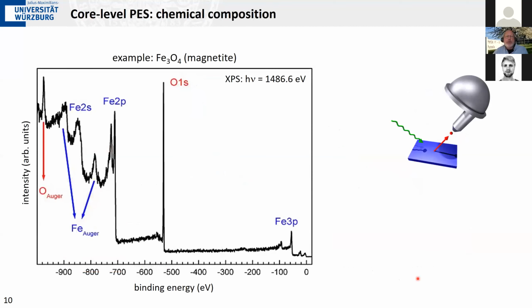Okay, this is what this looks like if you look on a large energy scale. This is an example: an XPS, X-ray excited photoelectron spectrum from magnetite, which is an iron oxide. In your spectrum, this is the current or the intensity of the photoelectrons versus the binding energy. In the actual experiment, you first measure them, of course, as a function of kinetic energy, but then you can transfer this energy scale into a binding energy scale.